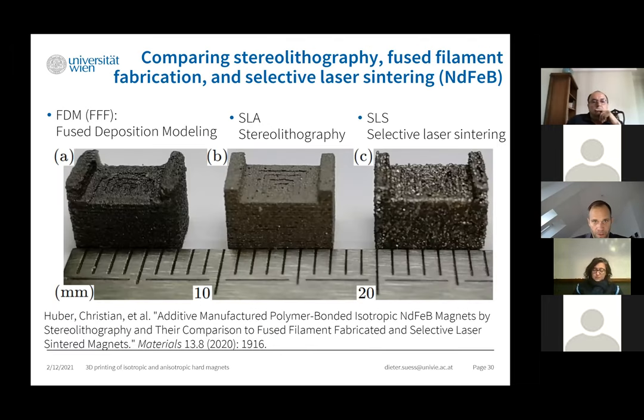And the last method I want to compare is stereolithography, where we used a photoresin and put the neodymium iron boron Magnequench powder in again and cured it with ultraviolet light. If you just look at the figure here, you see that the fused filament fabrication magnet has much lower lateral accuracy than the stereolithography produced sample. In between is the selective laser sintered magnet.